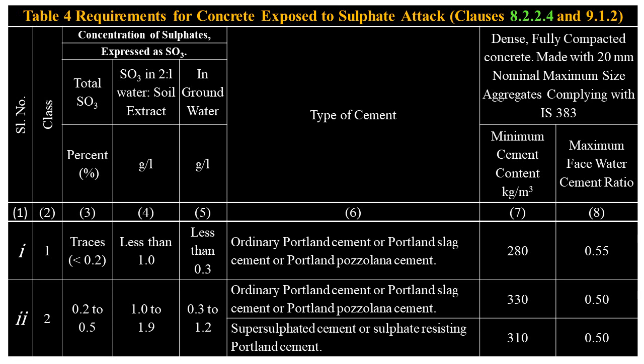SO3 in groundwater, less than 0.3 grams per liter. Type of cements: ordinary Portland cement, or Portland slag cement, or Portland pozzolana cement. Minimum cement content, 280 kilograms per cubic meter. Maximum free water cement ratio, 0.55.